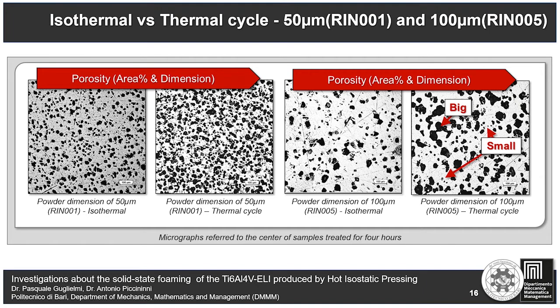To better understand, regarding the material with the titanium powder dimension equal to 100 micron, a non-uniformity of the porosity sites was recorded. In fact, they apparently seem to be larger than those of the other material, but the presence of very small porosity determines a reduced average value.